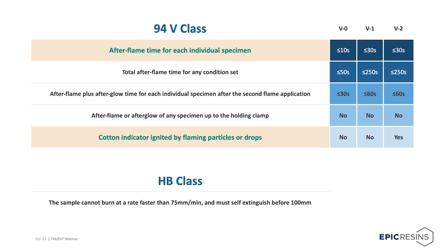This table outlines the test results for classification within the UL 94 series. Though all the criteria of the test are important, the two most critical results are the after flame time for each incident of the flame and ignition of the cotton. Specifically, for V0, the after flame time must be below 10 seconds and no drips can ignite the cotton bundle.